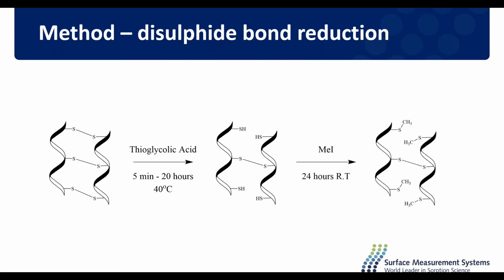So our next step in this synthesis was to methylate these samples with methyl iodide, which is quite a bit of a nasty synthetic step, but it does the job. And so now we have our nicely methylated hair, which has been reduced to different degrees.